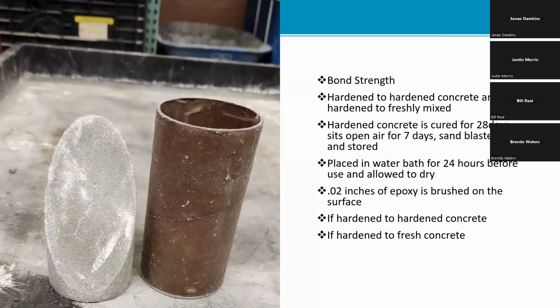So the hardened concrete is cured for 28 days, and you can cure this for 28 days or even longer. It depends on when you're finished with it. You can sit it on a shelf until you're ready to use it. But after that 28-day cure time, it sits in the open air for 7 days. It's sandblasted, because you want that epoxy to adhere to the surface of that concrete. Once you sandblast it, you place it in water for 24 hours, and then you allow it to dry.